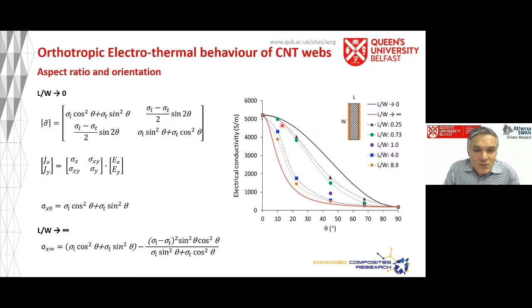So what we did then was, these are the theoretical curves. Of course, when I say theoretical, we do have to actually base those theoretical curves on two measurements, the one at 0 degrees and the one orthogonal to get our extremum points. But then if I start looking at the different samples I mentioned earlier, you can see that, as you would expect, with an aspect ratio of 1, 4, 9, etc., you fall between those two curves as expected.